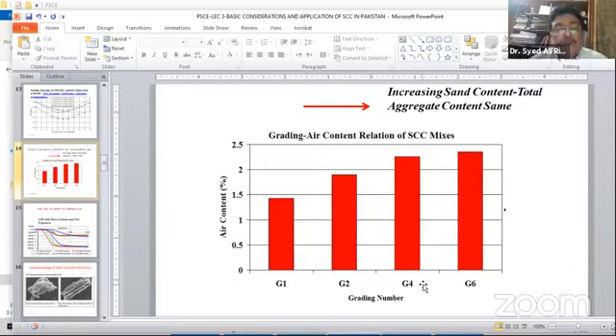Thank you, sir. So in the vertical axis, there is an air content, and here I have used 4 different types of grading: G1, G2, G4, G6. Probably this is 50-50, 50% coarse, 50% fine sand, and this is 55% sand and 45% coarse aggregate. So as you increase the quantity of sand, you will increase the entrapped air content as high as 2.3 or 2.4, even in self-consolidating concrete. So sometimes this picture can be taken advantage of,